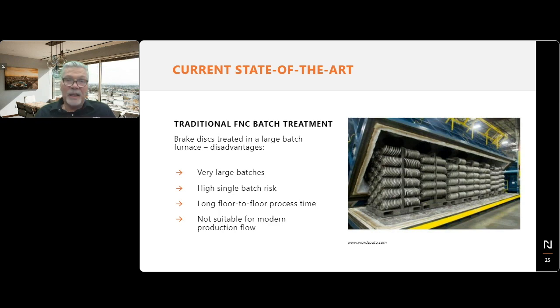The other big advantage is that it's sitting on a very solid sole, which doesn't show here very well, but there are circulation fans to maintain uniformity of temperature. So you can put humongous loads of rotors in one load, and the furnace will take 50,000 pounds perhaps of load easily. The negative point is that obviously it is very hard to heat up and to cool down, so the process time is really affected by this construction. It is not really very easy to automate. It has to be loaded with lift trucks and unloaded with lift trucks. And as such, it's not really adapted to an expansion of production into much higher quantities.